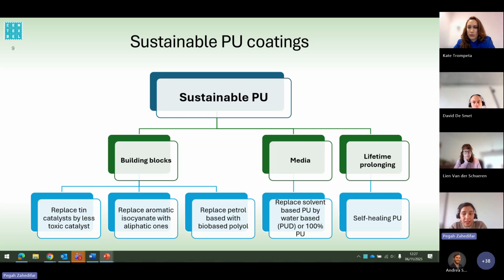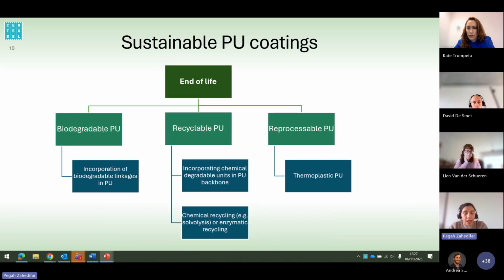For example, we can have self-healing polyurethanes that can extend the lifetime of the polyurethane, and in this way we can also have it more sustainable. The other approach is that we can affect the end of life of the polyurethane. For example, we can have biodegradable polyurethane by incorporation of biodegradable linkages or building blocks in the polyurethane. Or we can have recyclable polyurethanes, for example, we can incorporate chemically degradable units in the polyurethane backbone, or we can chemically or enzymatically recycle the polyurethanes that are produced, or we can reprocess the polyurethane.